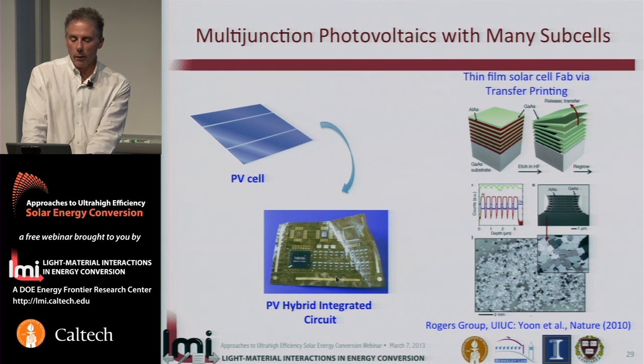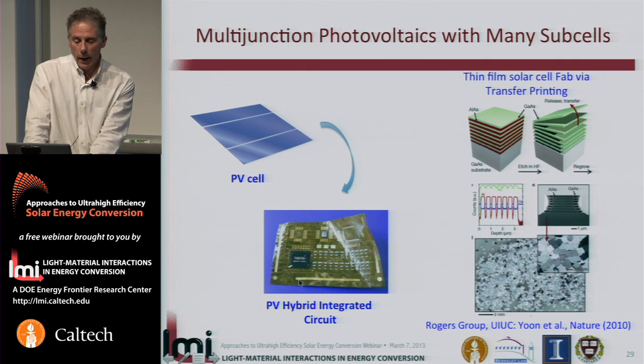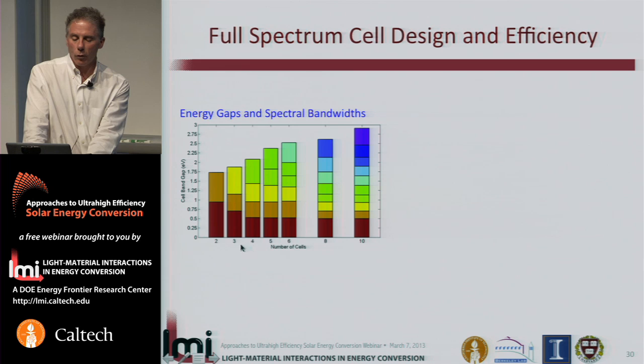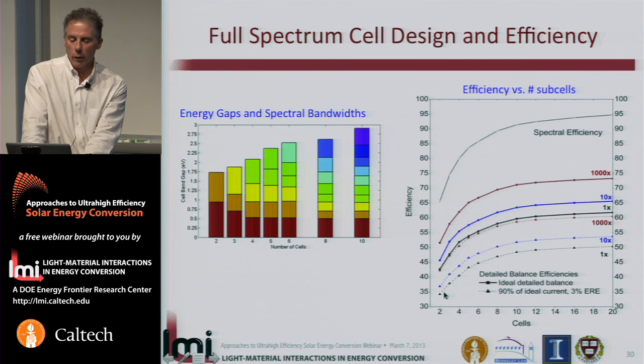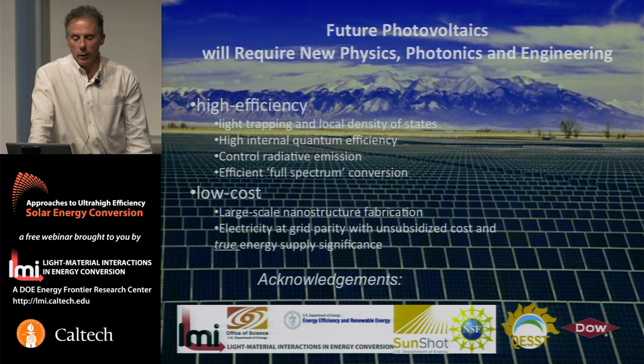And indeed, complex optoelectronic integrated circuits that are commodities are in front of us every day in the form of our flat screen displays on our laptops and projectors and so forth. And if we make cells that consist of not single or 2 or 3 or even 4 absorbers, but say 6 to 20 absorbers, one can define a series of spectral bands that creates, particularly combined with solar concentration, a substantial increase in the achievable photovoltaic efficiency for realistic quality materials. And so going from 3 or 4 junctions to maybe 8 junctions can yield the same increase in efficiency as is possible by solar concentration, going from 1 sun to 500 to 1,000 suns.